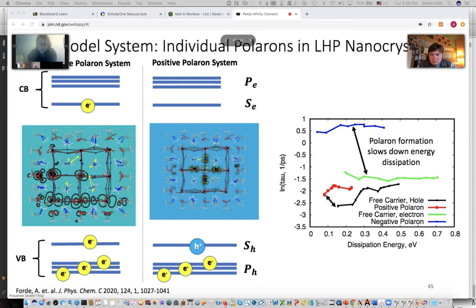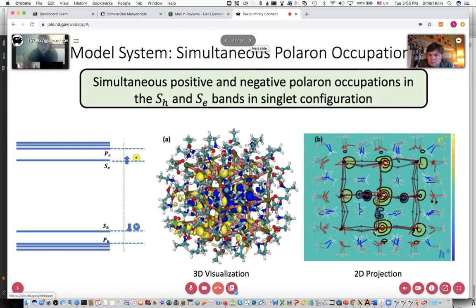And from this study, we did find that if you include explicit occupations in these bands, they do have a noticeable impact on the non-radiative dynamics. So this arrow comparing blue and green lines shows that if you explicitly account for charge in the conduction band, it slows down the non-radiative dynamics. And then same for the hole, comparing the black and red lines. So it's a system we've already worked on.